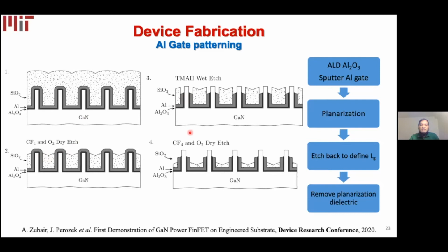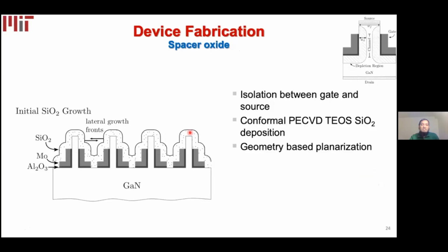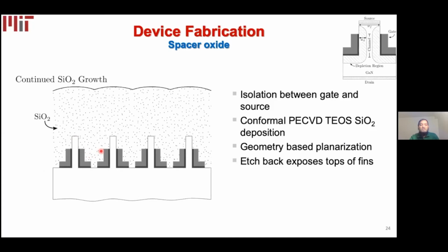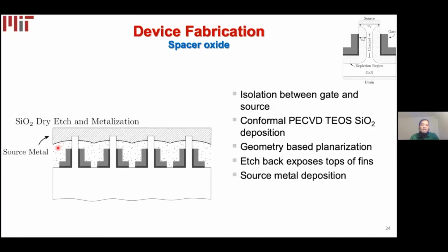And once we have our gate defined, the next step is the spacer oxide, which basically separates the gate metal from the source metal, which is on top. To do that, we again use a PECVD SiO2 solution, and we're using a TEOS precursor. And due to the use of TEOS precursor, the silicon dioxide actually grows conformally from the side walls. And as it keeps growing, it merges the front and nicely planarizes on top of the device. And after that, we can etch back. And once we expose the source region of the fins, we deposit our metal and finish the device fabrication.